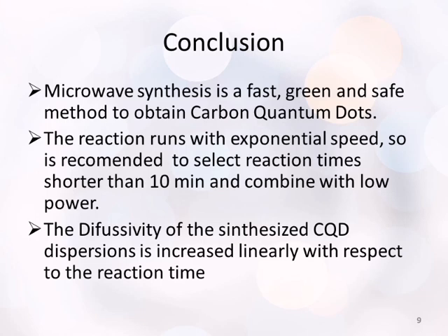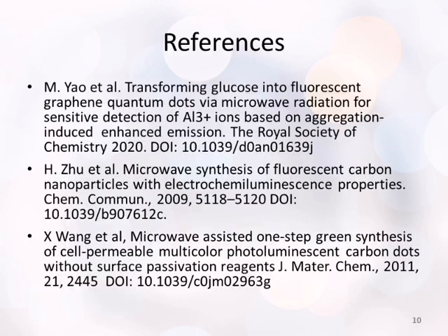Conclusions. Microwave-aided synthesis is a fast, green, and safe method to obtain carbon quantum dots. The reaction runs with an exponential increase in speed, so it is recommended to select reaction times shorter than 10 minutes and combine it with low power. The diffusivity of the synthesized carbon quantum dot dispersions increases linearly with respect to reaction time.